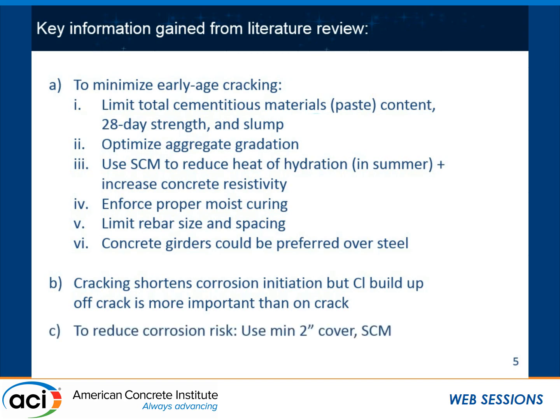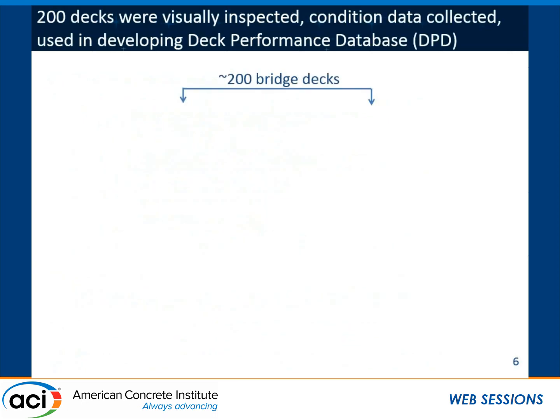To reduce the risk of corrosion, use a minimum of 2 inches of cover and supplementary cementitious material. And any remediation action has to take place before active corrosion starts. Once we are past the corrosion initiation period, repairing is not going to help us much because the steel underneath is going to keep corroding even if you repair the surface.